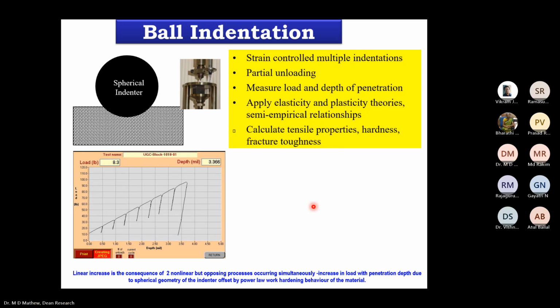So as the indenter penetrates the material, you measure the load, you also measure the depth of penetration. So you have two data. Your raw data is the load as well as the depth of penetration. If you are doing 7, every time you are penetrating, you will generate a large amount of data because continuously you are measuring the load and depth of penetration, and that is repeated 7 times or 9 times. That can vary. So in this way, you are generating a large number of load and depth data from one experiment. Once you have this data, then you can process it, apply elasticity and plasticity theories, also certain semi-empirical relationships, and you can derive the tensile properties, hardness, as well as the fracture toughness of the material.